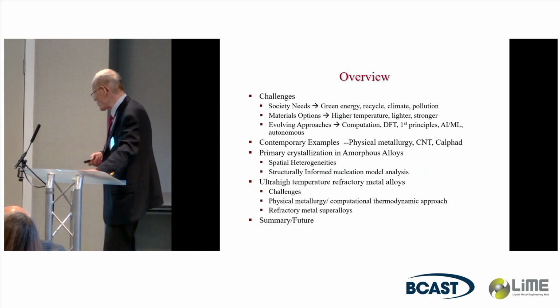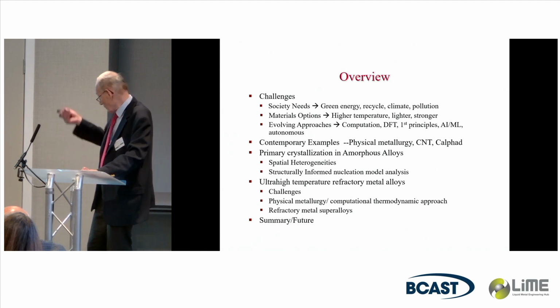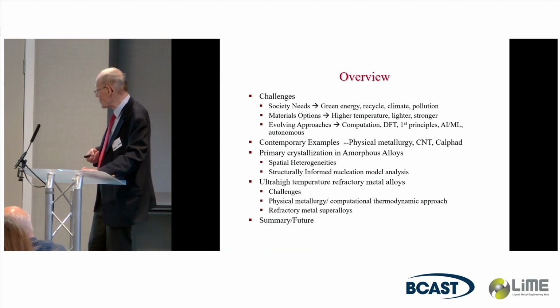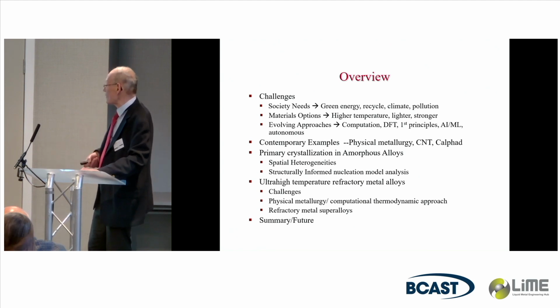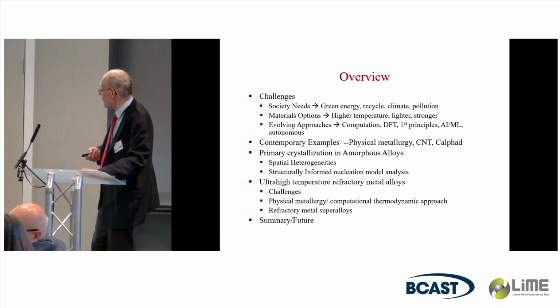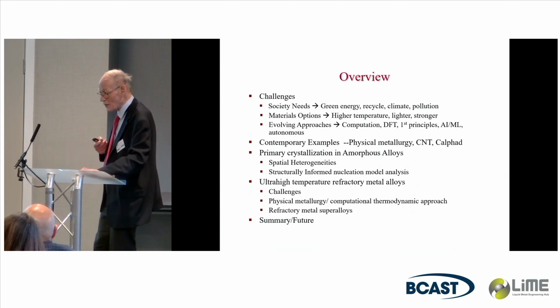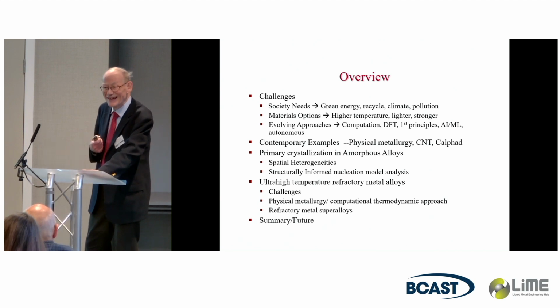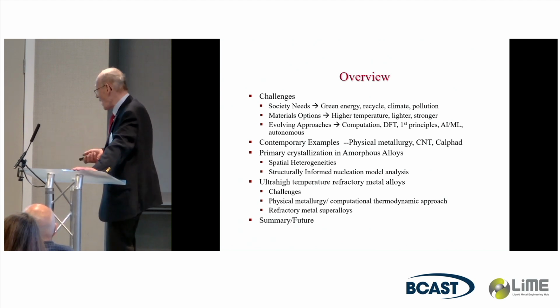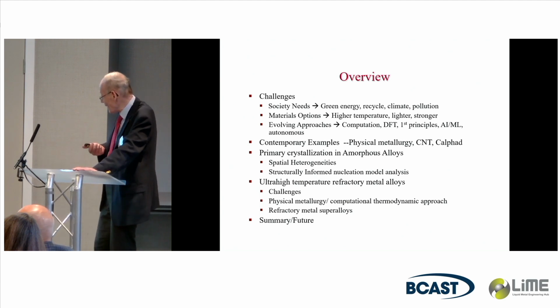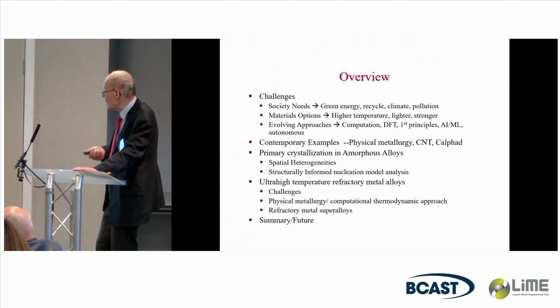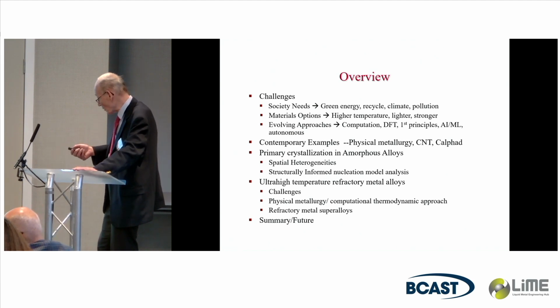And then ultra-high temperature refractory metal alloys. As we're reaching the limit of capability with nickel-based alloys, we have to go to higher temperatures. There are some ceramic developments, but there was a famous person, Chet Sims from General Electric, who one time commented about ceramics, dust to dust. You start with dust and you end with it. And here, again, we're using physical metallurgy and computational thermodynamics to develop what I would call a refractory metal superalloy.